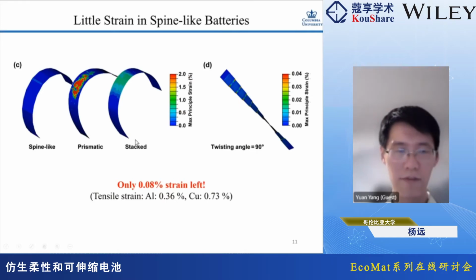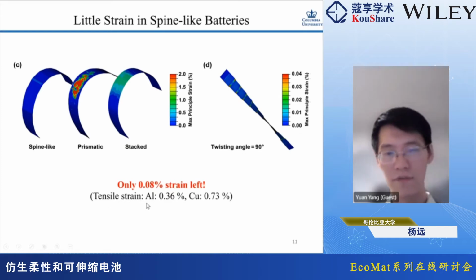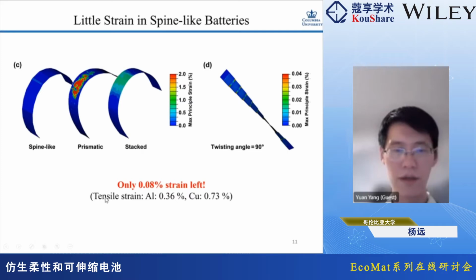To validate that it can be flexible and the strain inside is low, we ran finite element-based simulations. In the prismatic and stacking cells, the strain inside is pretty high, 2% and 1% respectively. But with the spine-like structure and the flexible interconnect, the strain inside is very low, only about 0.08%. During twisting, the strain inside is also very low. This remaining strain is much less than the tensile strain of the metal substrate, so it can be pretty robust, and we don't need to introduce new materials inside.